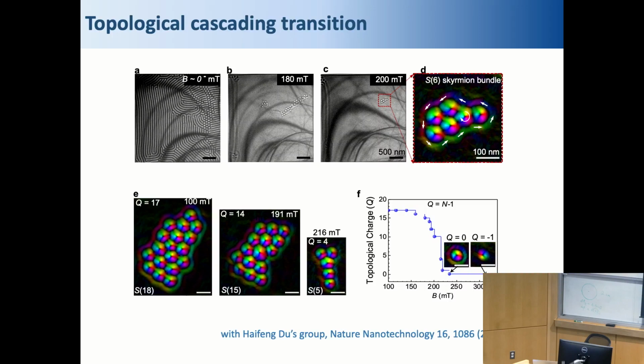Starting from this configuration, you gradually increase your field. And there's a cascading topological charge change by annihilating skyrmions inside one by one. 17, 16, 15, and this is stepwise. Eventually, you get a skyrmion with topological charge 0. But if you further increase the field, this central skyrmion, because as I said, it has a central spin pointing in the same direction as the external magnetic field, it's not stable, it will collapse. And eventually, you end up with a conventional skyrmion with a central spin pointing opposite to the external magnetic field. It has topological charge -1.